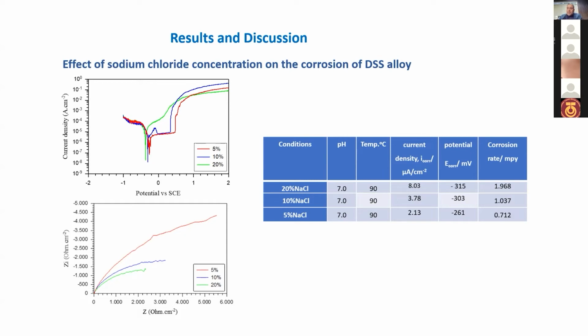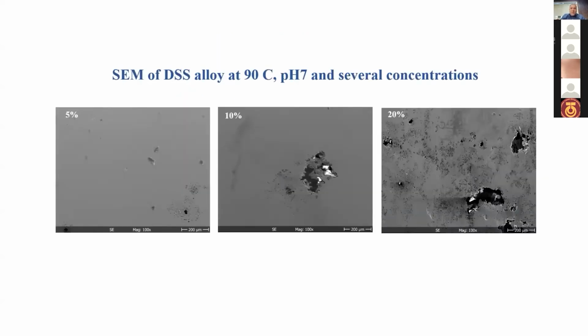We note a significant decrease in the electrochemical impedance of duplex stainless steel with the increase in the concentration of sodium chloride. Also, the SEM, or scanning electron microscope, images of duplex stainless steel support our results in the electrochemical test. We note that the corrosion pits increase in size and number with increasing chloride concentration, as we show here, that the pits increase significantly in size and number.